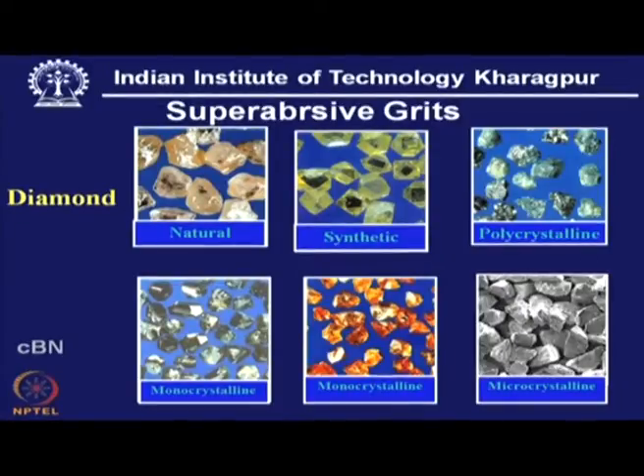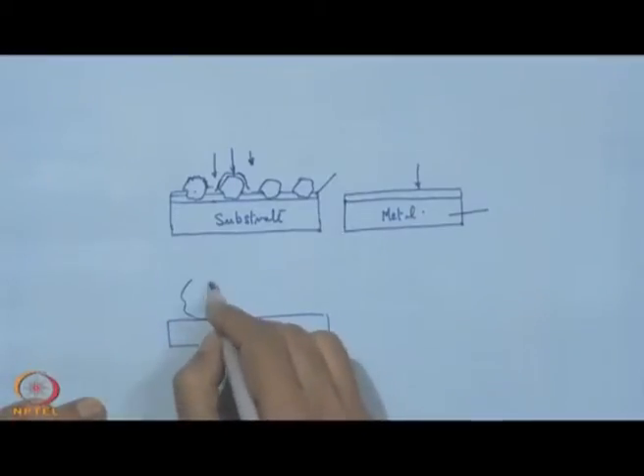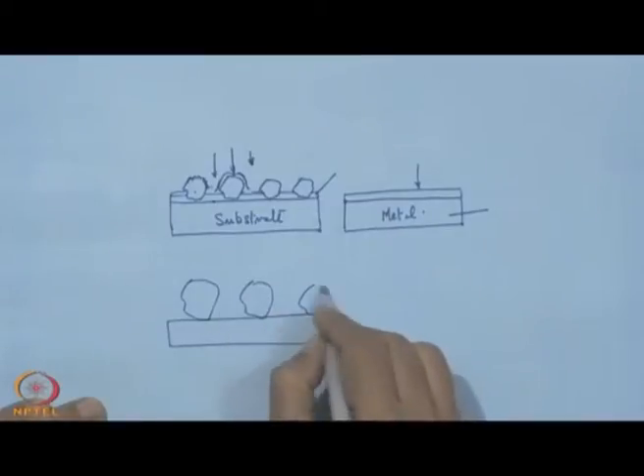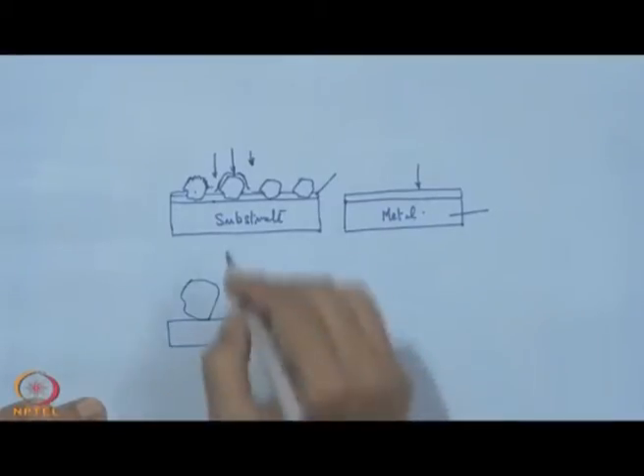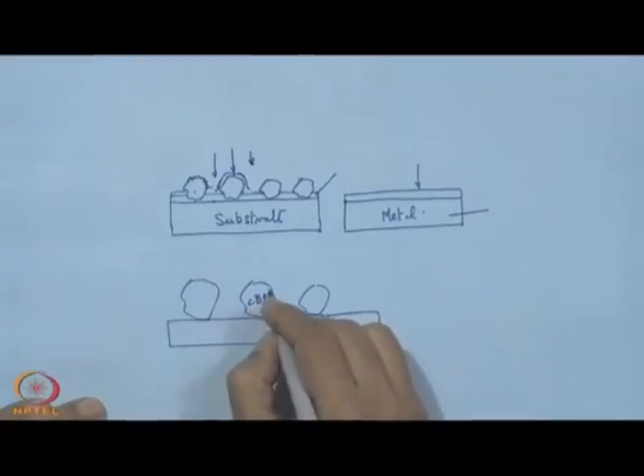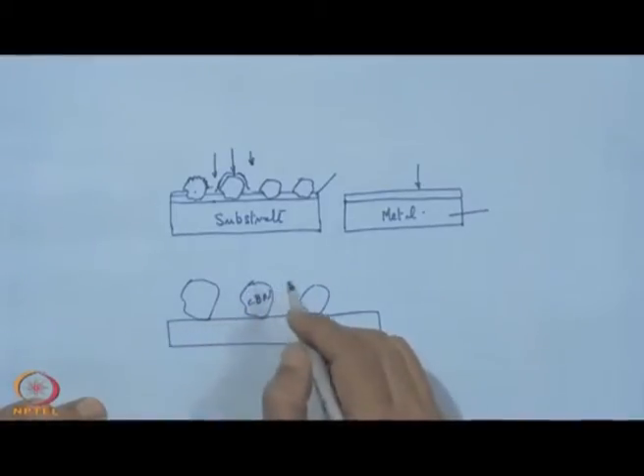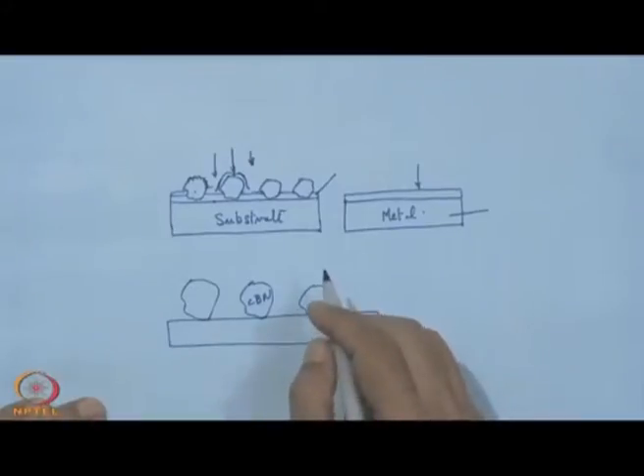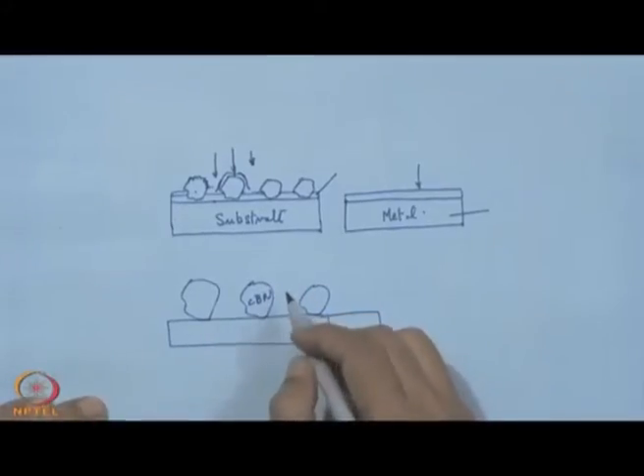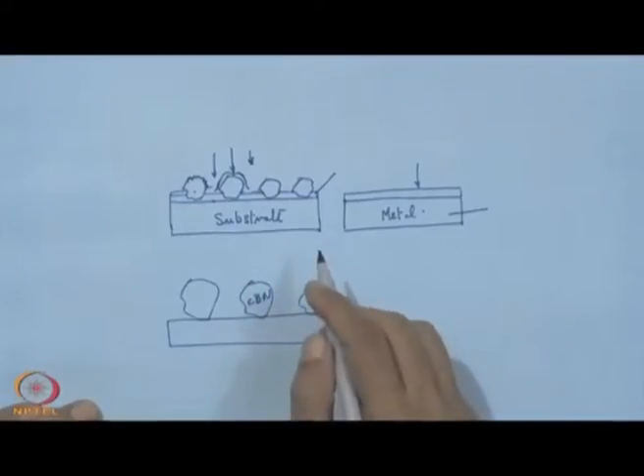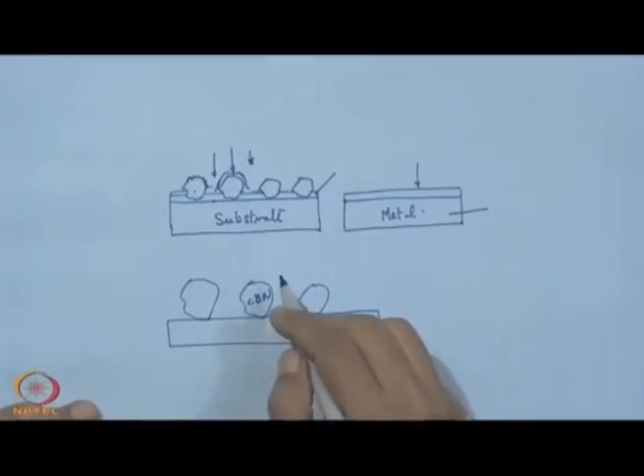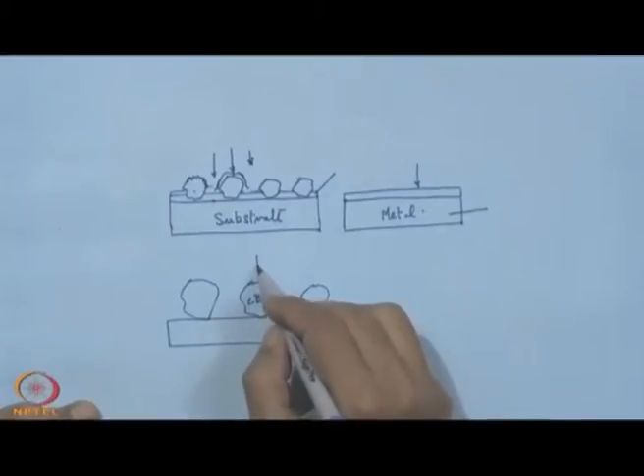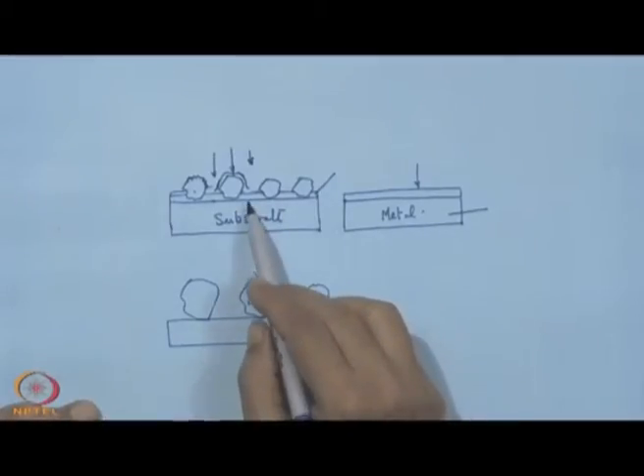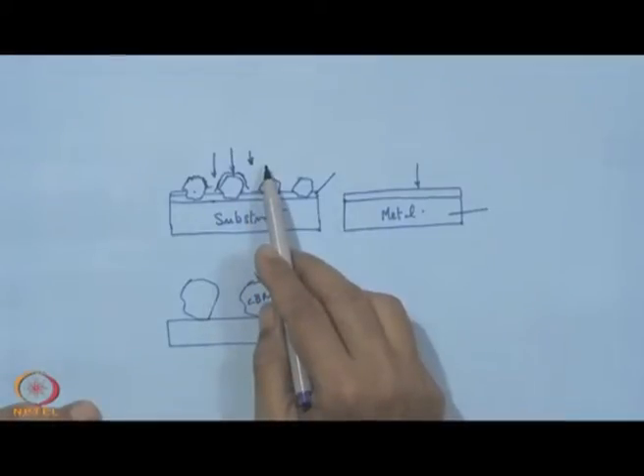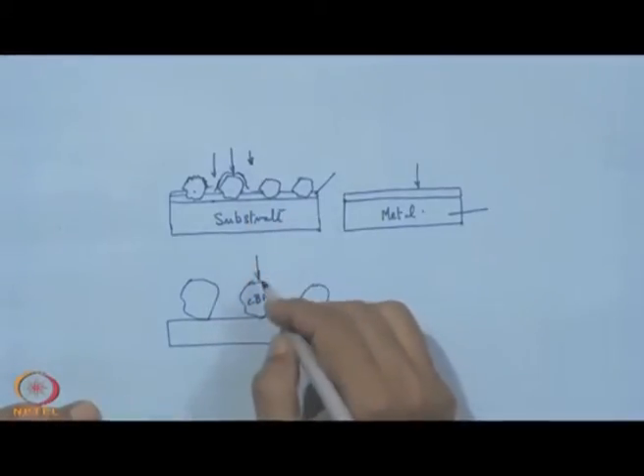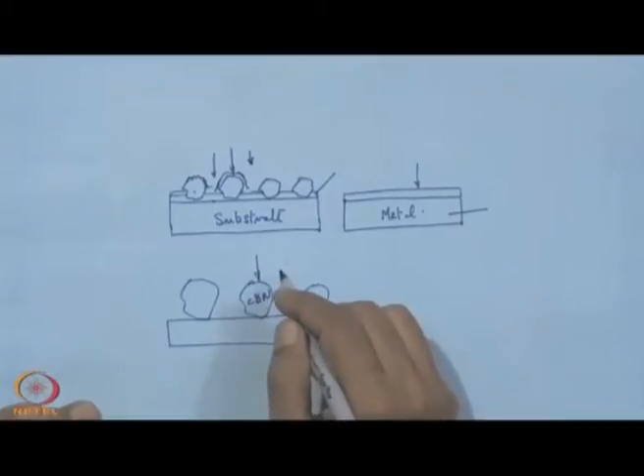So, on this surface if we place this CBN particle, and if it has excess boron, then that could become problematic, in that this surface boron, excess surface boron, can also lead to electrical conductivity, and in that case also deposition of this galvanic metal from this electrolyte, that cannot be just ruled out.